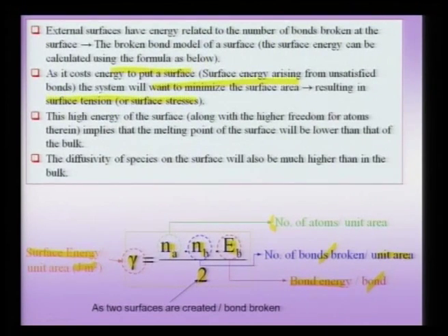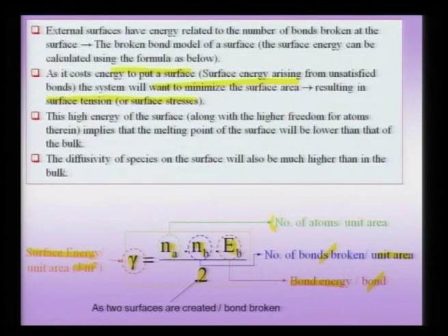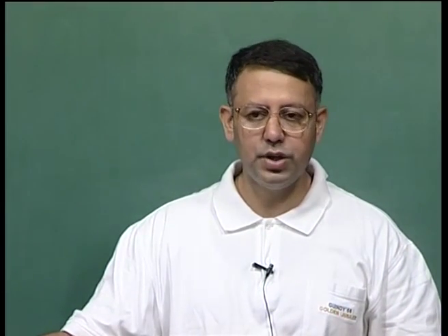But nevertheless, the origin of the surface tension is coming from the energy which is expended when I am trying to put a surface. Now, we will make a calculation showing how this formula can be used in the calculation of surface energy, but you have to remember this is what is called a broken bond model. In other words, I do not incorporate any other effects like surface relaxation after the cut is made, or any kind of reconstruction effects, and therefore, this is the simplest kind of formula I can deal with.